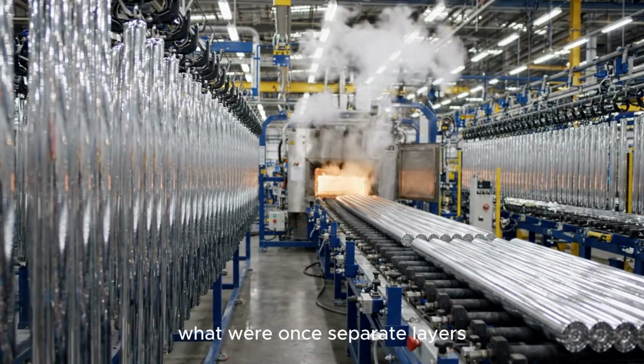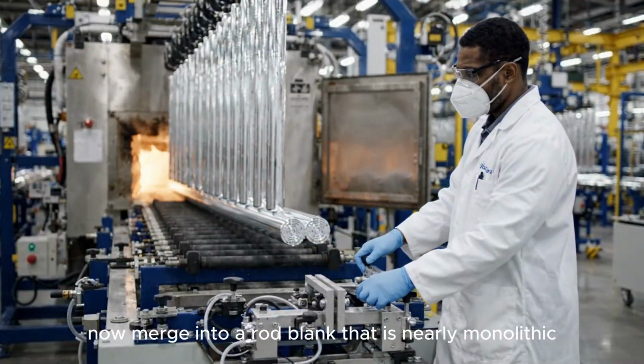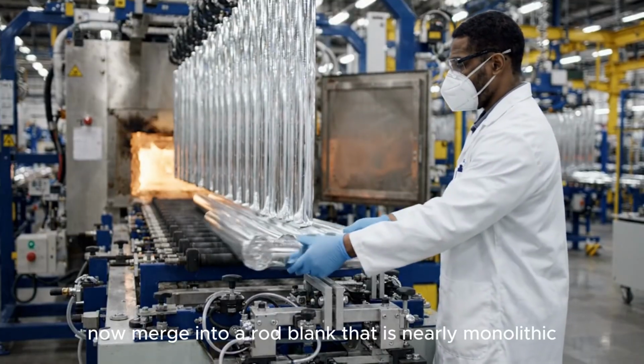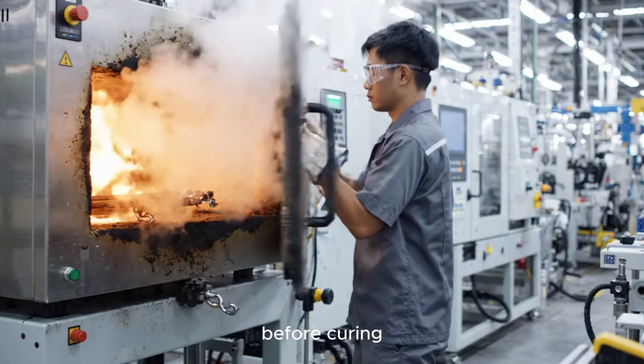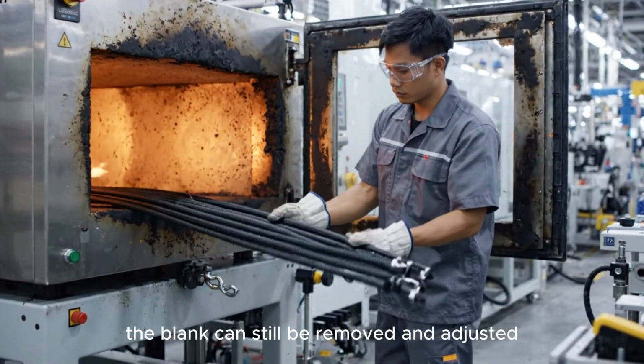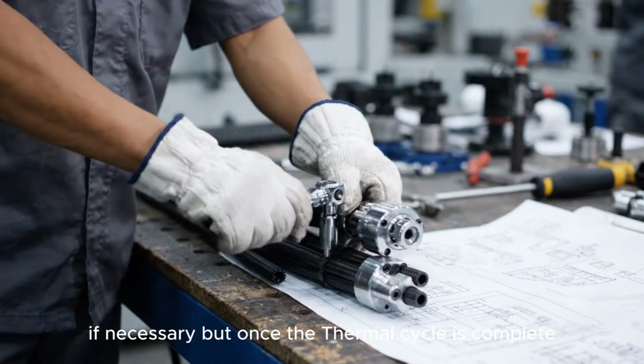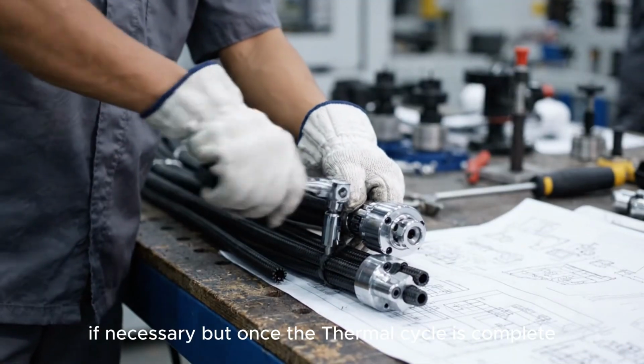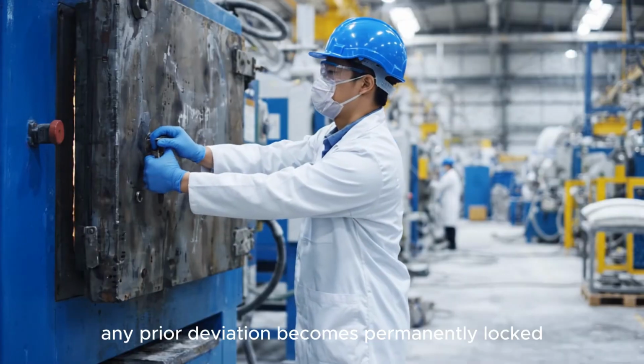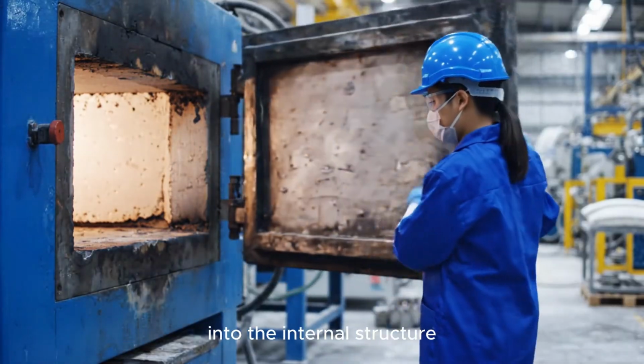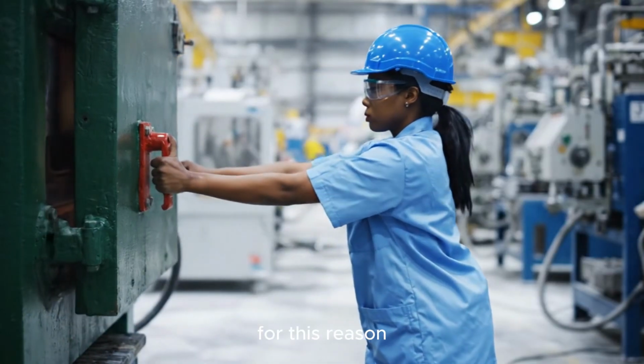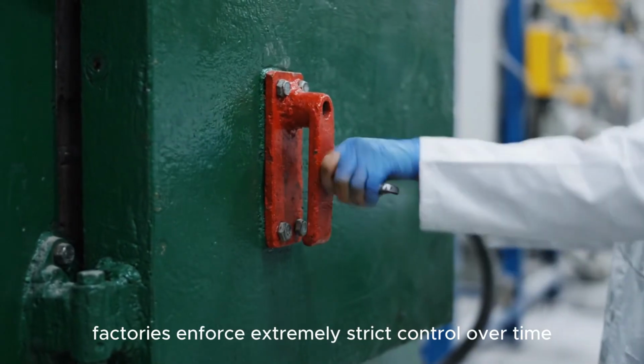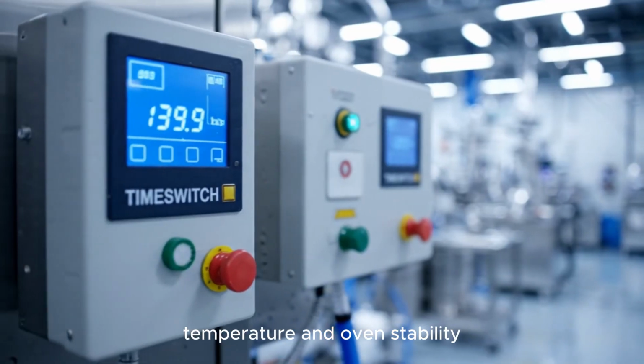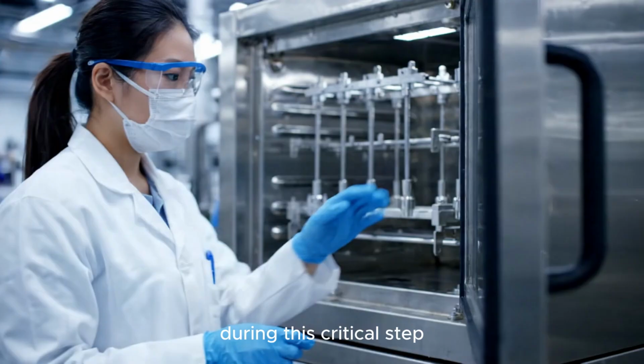What were once separate layers now merge into a rod blank that is nearly monolithic. Before curing, the blank can still be removed and adjusted if necessary. But once the thermal cycle is complete, any prior deviation becomes permanently locked into the internal structure. For this reason, factories enforce extremely strict control over time, temperature, and oven stability during this critical step.